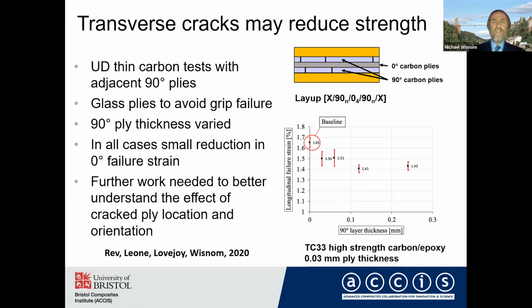the failure strain. So in this study here, Thomas Rev did some cross-ply specimens. And in all these specimens, we've got 0 degree plies in the middle here, and then next to it, we've got some 90 plies. And then we need some other plies and some glass to avoid the grip failure. And what he did in this study was to vary the thickness of this 90 degree ply, which is next to the 0 degree carbon. And what you see here is the longitudinal failure strain, the tension strain, as a function of this 90 degree ply thickness. Baseline is up here, about 1.65% for this material.